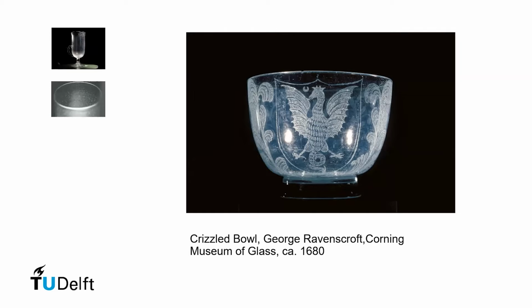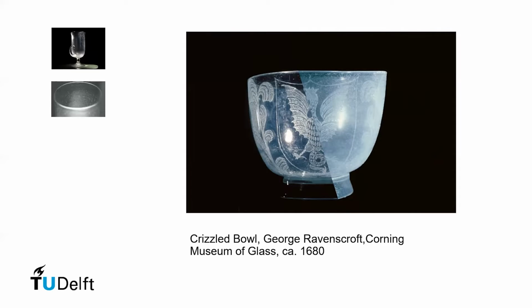And you have seen this glass, but it has been moved, and I don't know if I get the order right, but it moved from one location to another where the humidity was slightly lower in the final destination. So what happened is that if you click now, you'll see an animation, and you can see more clearly what has happened to the object, where it turned from apparently pristine condition to very heavily degraded, what we refer to as crizzling, which is the formation of a network of cracks on the surface. But at the time of the change of location of the object, it wasn't clear that this object was susceptible to show this behavior. Next slide, or next click.